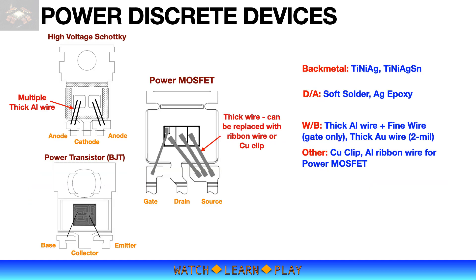High voltage Schottky diodes, high power MOSFETs, and BJTs are examples of power discrete devices. These devices have large die size and operate at high current and dissipate a lot of heat. Most power devices have backside metallization suitable for soft solder and silver epoxy die-attach process. Power discrete devices have large bond pads suitable for multiple thick aluminum bonding wires, aluminum ribbon wire, or copper clip bonding. Illustrations on this slide are examples of thick aluminum wire bonding configuration.